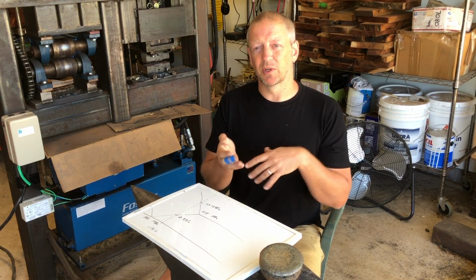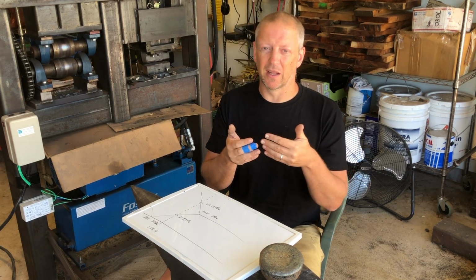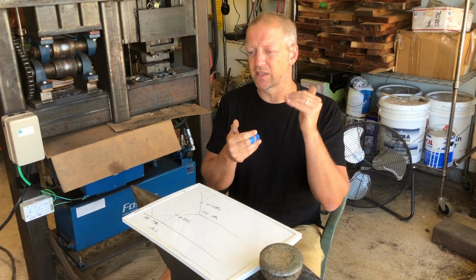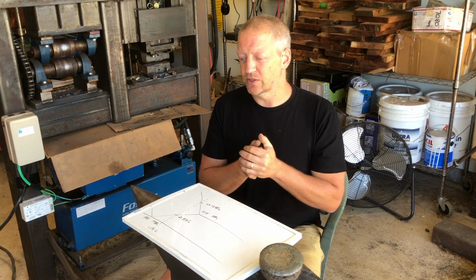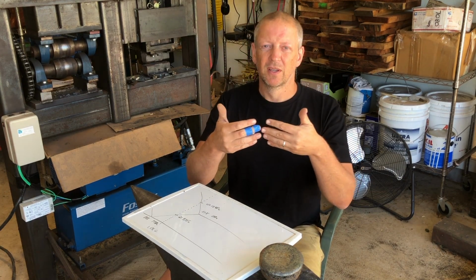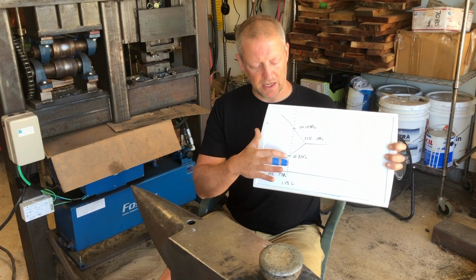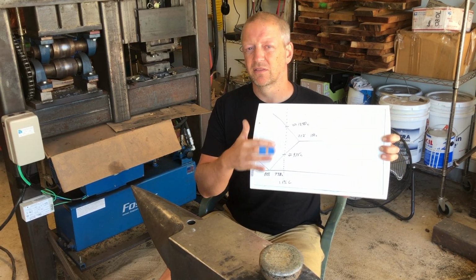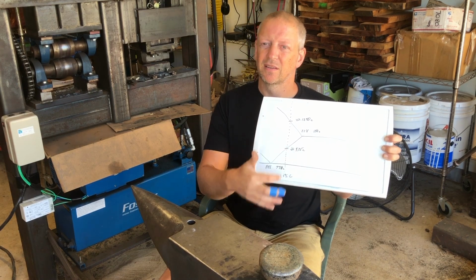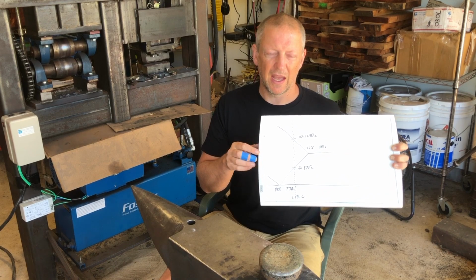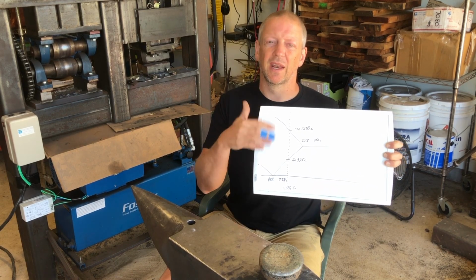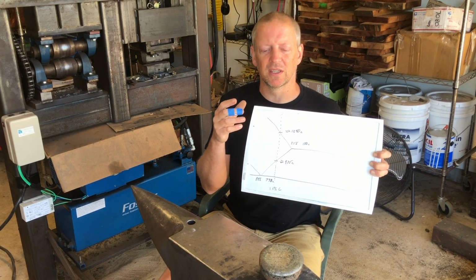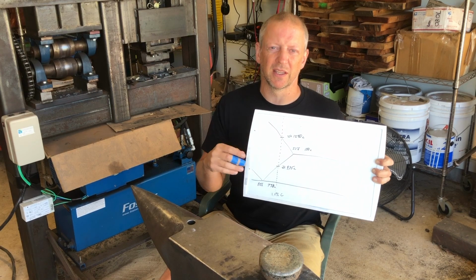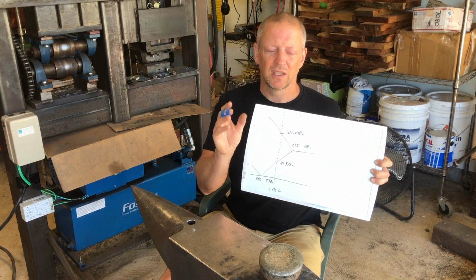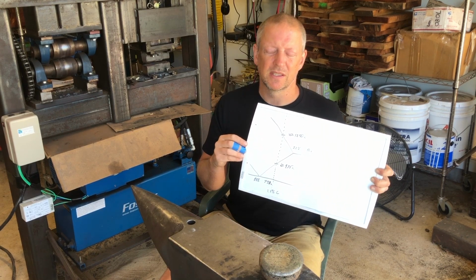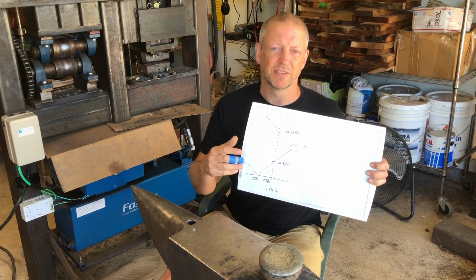You can offset this to some degree by adding more of those carbide forming elements, particularly ones that form carbides at higher temperatures. What those do is, as you're cooling down, as we're coming towards the ACM line, the carbides form first, and then maybe you get graphite. So having those carbide forming elements can help mitigate nickel content. So anytime that I'm doing an ingot where I'm adding meteorite or something like that, where I'm going to have nickel in the ingot, I always bump my CFE levels a little bit to offset that some.